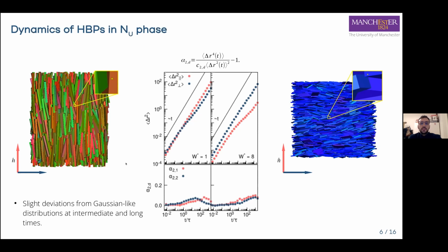We also computed the non-Gaussian parameter, which gives us an estimation of how the probability of particle displacement deviates from an expected Gaussian-like distribution. And we observed that in this case, despite the formation of temporary caging effects, we didn't see strong deviation from Gaussian-like distribution. So we could say that over all the time scales that we investigated, the particle displacement is Gaussian-like, despite the formation of temporary caging effects.